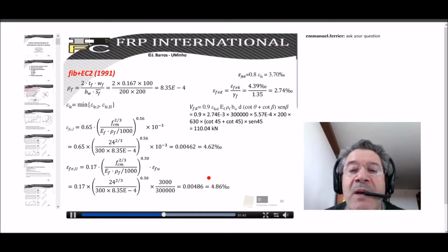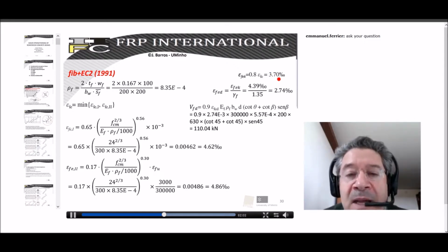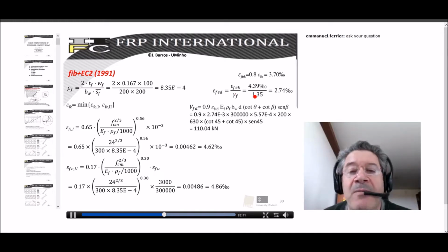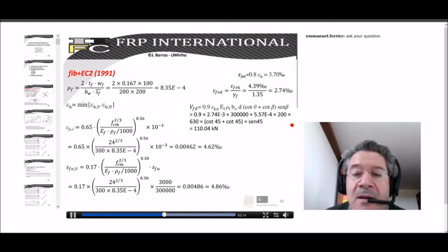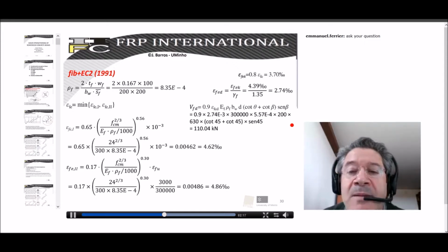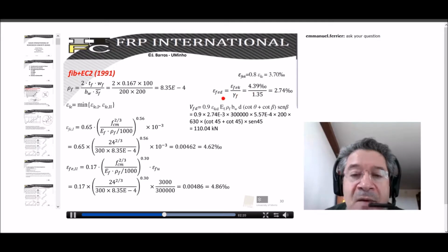Then I need to obtain the characteristic value, and the characteristic value of the effective strain is 80% of the effective strain, and then we obtain 3.7 per mille. Finally, in order to obtain the design value of the effective strain, we divide the characteristic value by the gamma factor, that for this case is 1.35. And we obtain the value of about 2.7 per mille. Consequently, if we replace this value in the equation that is provided by the FIB, we finally obtain a value of 110 kilonewtons.